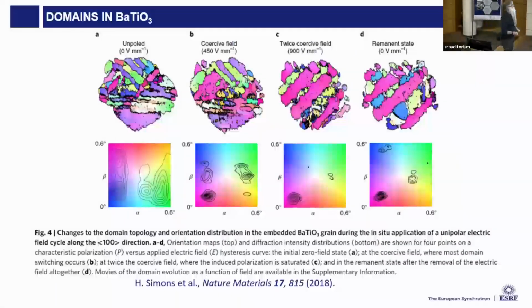And then we can, of course, do this in situ, following this domain arrangement through the hysteresis loop. On the left side, we have the unpoled divergent state, if you want. Then you start to apply electric field. You start the formation of domains. You go to twice the coercive field. You have a very strongly dominant these pink domains.